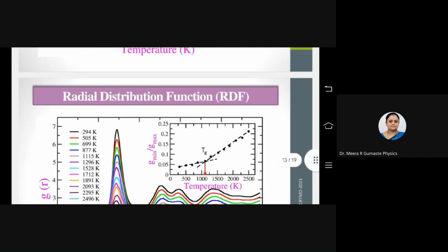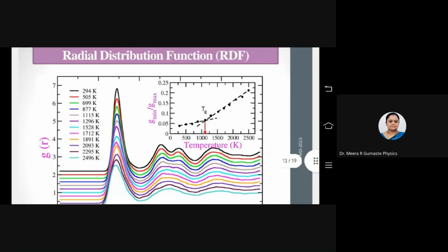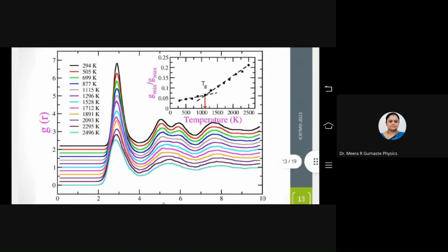To mark the GFA, the glass forming ability, we need to know the liquidus temperature and the glass transition temperature. The ratio of these two gives us the glass forming ability of any material. So TL is calculated from this melting curve, and for TG, we have calculated it from this second curve, which is the radial distribution function, g(r). For the experimentalists, I'm telling this: it is basically the Fourier transform of the structure factor. That means it gives the nearest neighbor arrangement of the atoms.